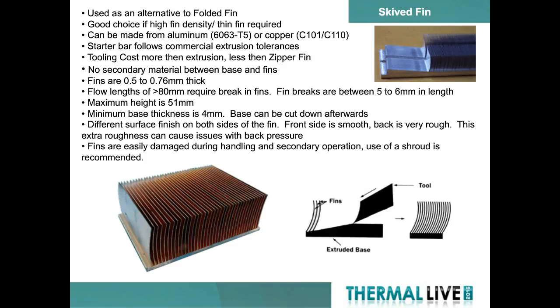We start with a block of aluminum or copper. There is a tool that comes across the top of the part, and it raises the fin. It basically slices down into the base and raises up a small burr. The fins typically are between 0.5 and 0.7 millimeters thick, and you have a height of 50 millimeters, or about 2 inches, as a limitation. If you want a taller heat sink, that can be done, but typically the fins end up being closer to 2 or 3 millimeters thick, but you do end up with that solid base at the bottom.